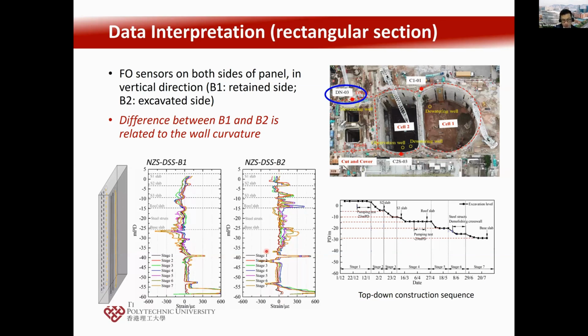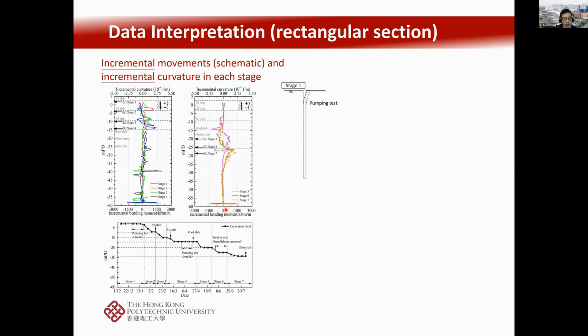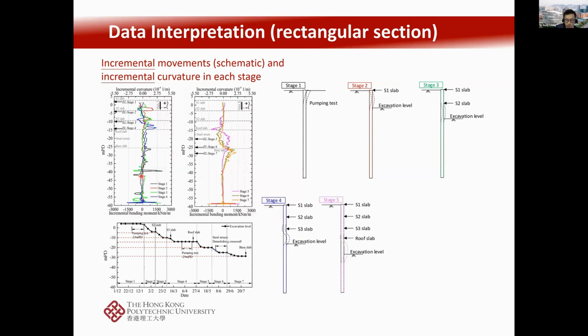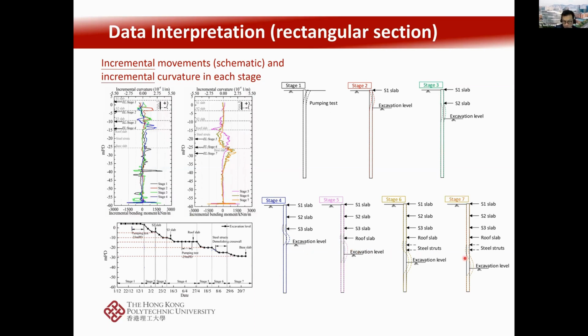And the different colors here basically correspond to different stages of the excavation. So using these differences between the strains in the front side and the back side, we'll be able to calculate the curvature and therefore the bending moments. So stage 1, the curvature is represented by the black line here. And then stage 2, in a top-down construction, we have a slab at the top and some excavation, and this curvature in red is captured by the fiber optic readings in red. And stage 3, more excavation, the green profile of the incremental curvature is also captured by the green profile of the fiber optic measurements. Similarly, we go deeper, stage 4, stage 5, 6, 7, the curvature in different colors are also captured by the readings of the fiber optic cables.